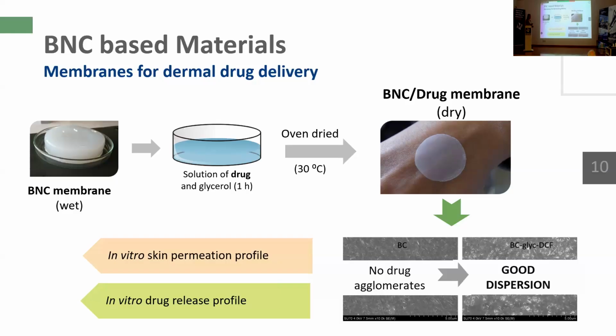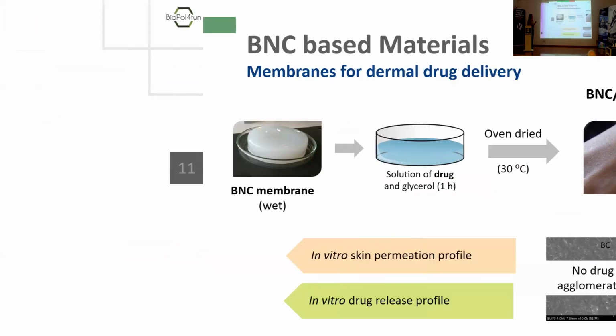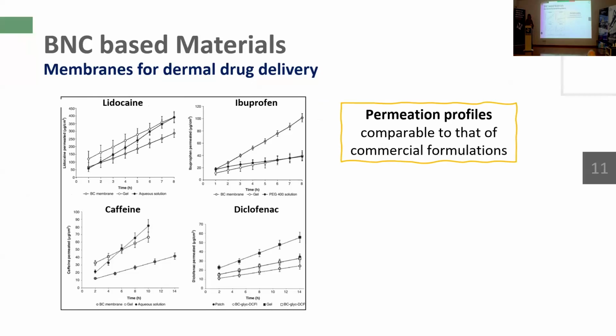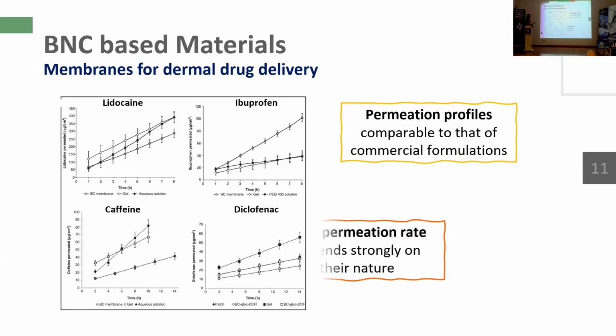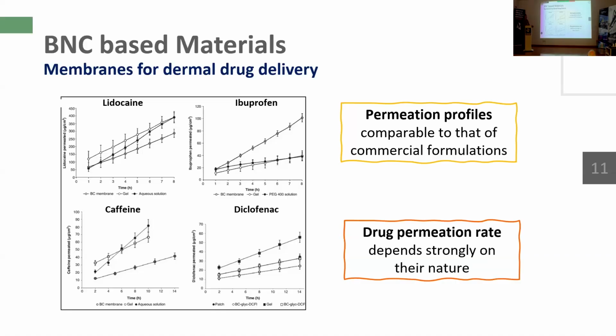And even in most of the cases that I refer, the permeation profiles that we evaluate using ex vivo human skin and these Franz diffusion cells are very comparable to commercial formulations that we use to compare the performance of our membranes. And in fact, they can be used as alternatives to these formulations because we have very comparable profiles. We realize that the drug permeation rate depends essentially on the chemical nature of the molecules and the interactions that are established between the molecules and the fibers.